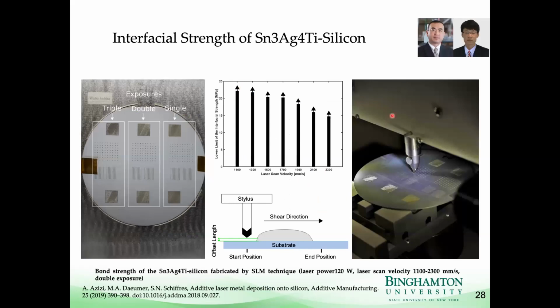We've also looked at the mechanical properties in collaboration with Changhong Ke and his team. And one of the things that we found that was quite interesting is that when you try to shear off little pins that are printed onto silicon, we found that it didn't break at the silicon metal interface. It actually sheared inside the tin. So this shows that the bond is actually quite strong between the tin alloy and the silicon.